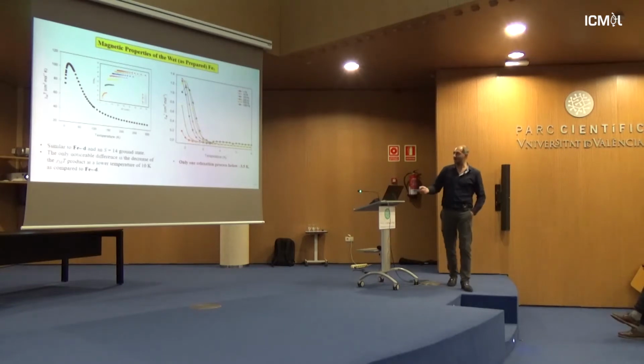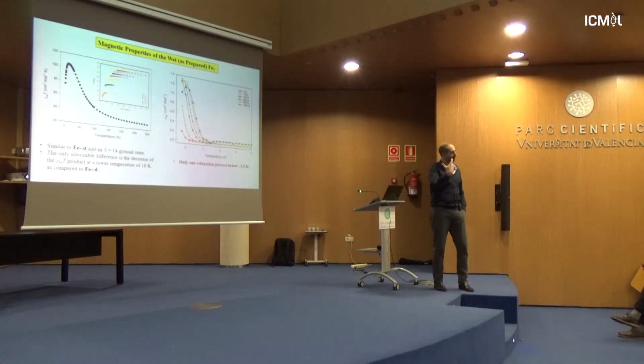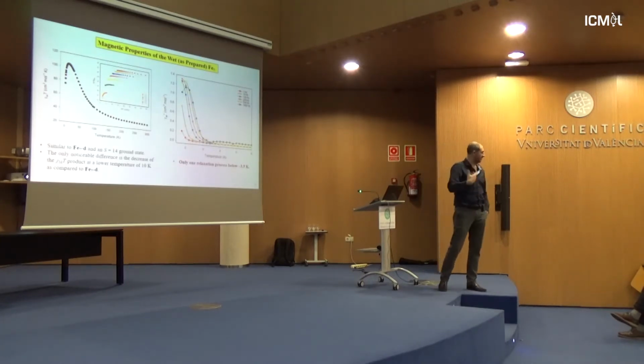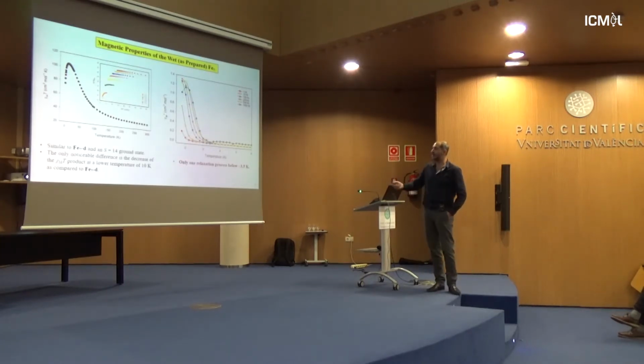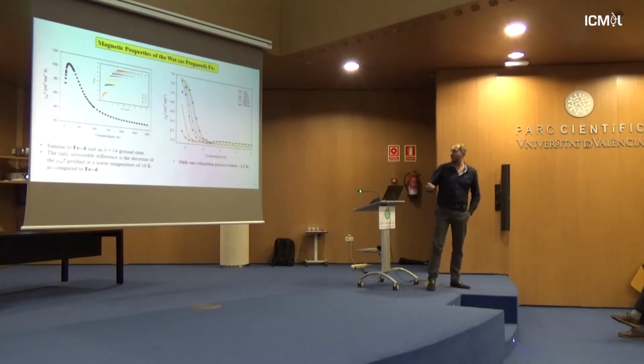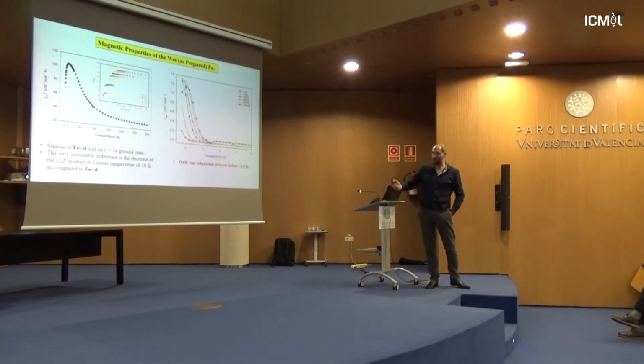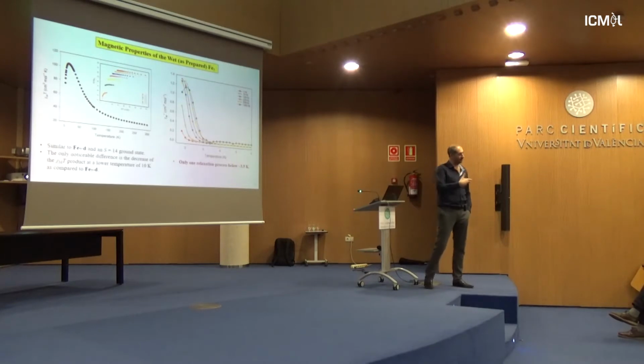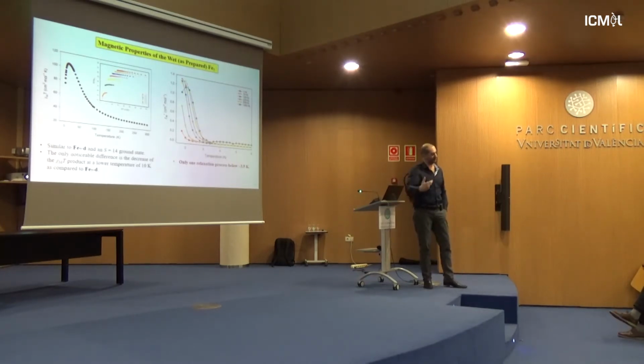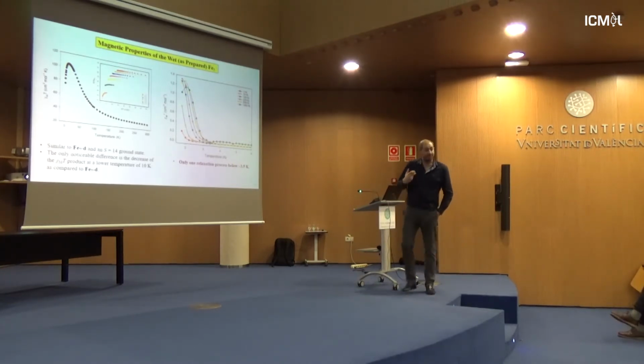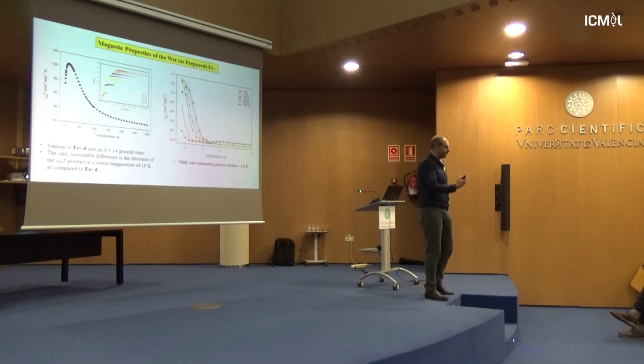In the wet compound, we see the same chi-MT as before. The ground state, of course, remains the same. Nothing has changed. The azides are there. They contribute to the ferromagnetic coupling. The magnetization is the same, but only the low temperature relaxation. We only see 1 relaxation below around 3 Kelvin, which is the low temperature one. We don't see the high temperature relaxation. So that, with the current state of our studies, allowed us to get some tentative conclusions.